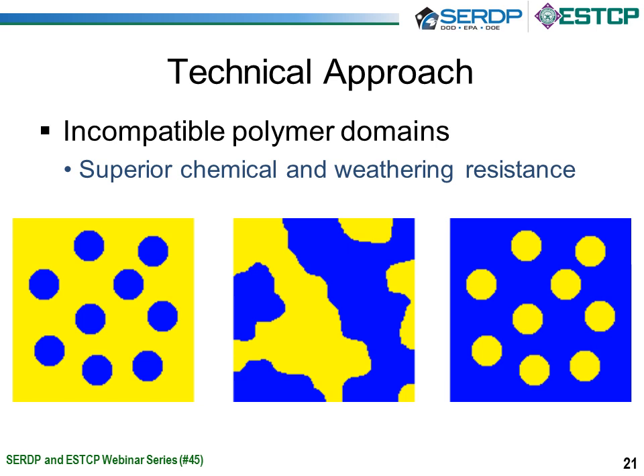The other thing that we did is we needed to have ultimately a fairly low gloss clear coating. So there had to be what we call incompatibility. And so what we see in these depictions is what we were shooting for, to have one resin system inside the other, to have a resin system that lowers the gloss. And what we ultimately found out, and you'll see later, is created some surface roughness by having resin systems that were incompatible.